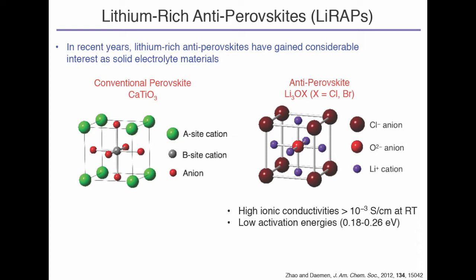The reason these have gained so much interest is because of an initial paper that was published in 2012 in JACS. Now, if we think about a conventional perovskite, the most common perovskite that we know is calcium titanate. All we need to know about calcium titanate is that on the A and the B site, we have metals, so cations, and on the anion site, we have oxygen. Now, to make an anti-perovskite, we take that structure and turn it upside down. So wherever we had a cation or a metal before, we now have an anion, and vice versa. Wherever we had an anion, we now have a metal. If we do that, we can produce this anti-perovskite, Li3OX, where X is something like chlorine or bromine.